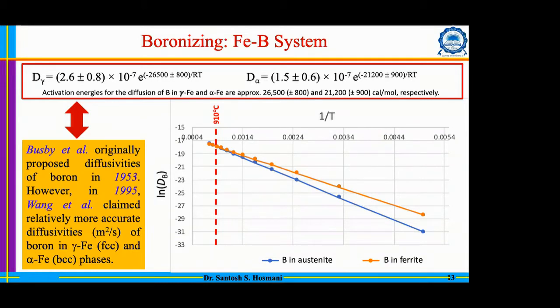And that is because the activation energy barrier for the diffusion or migration is quite high for the FCC matrix compared to that of the BCC matrix. And that matches well with the phenomena associated with carbon and nitrogen diffusion. Originally, this diffusion concept was introduced in 1953. However, that equation had some error, and later on it was corrected.